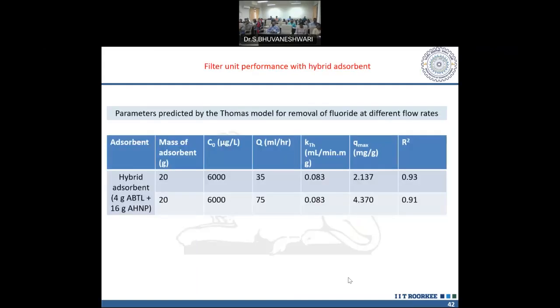And what we see are the parameters predicted by the Thomas model for removal of fluoride at different flow rates. You see that the peak is 4.37 for this, and 2.137 on average as well. If this specific value is more than 2, then it can come to the market.